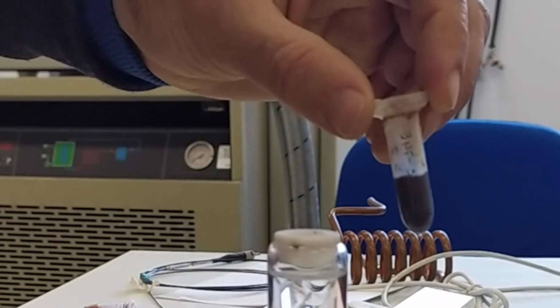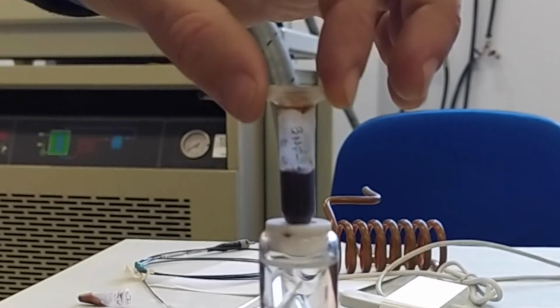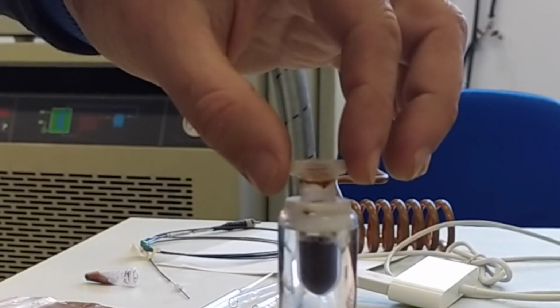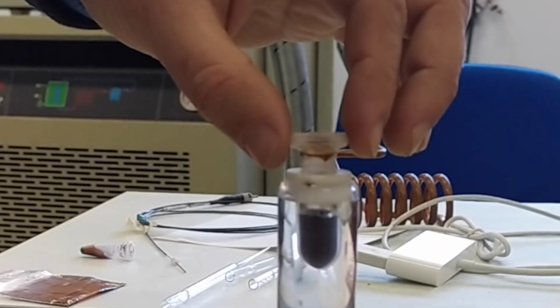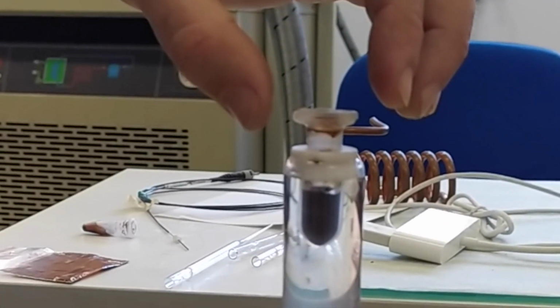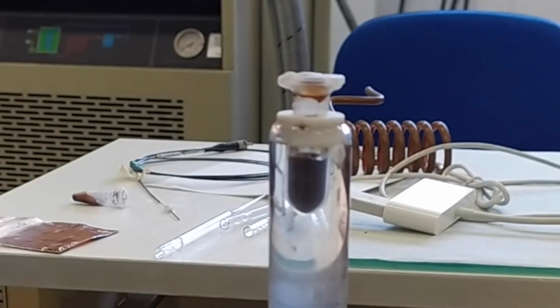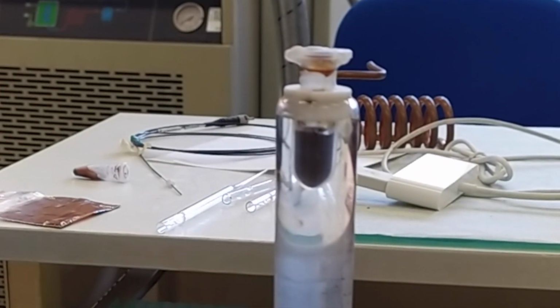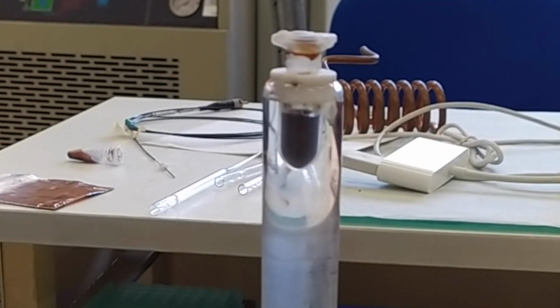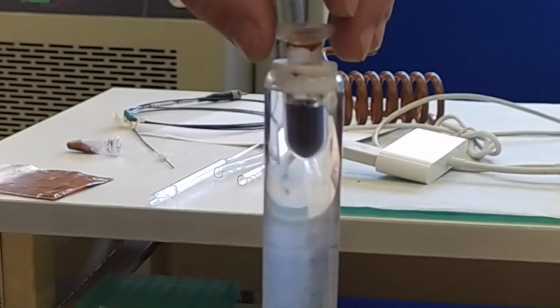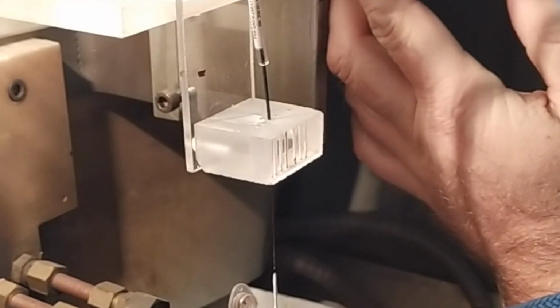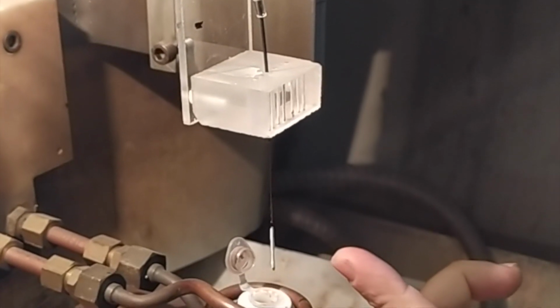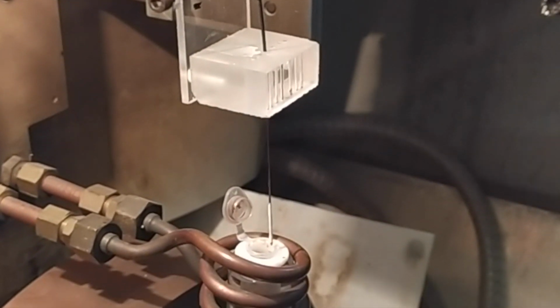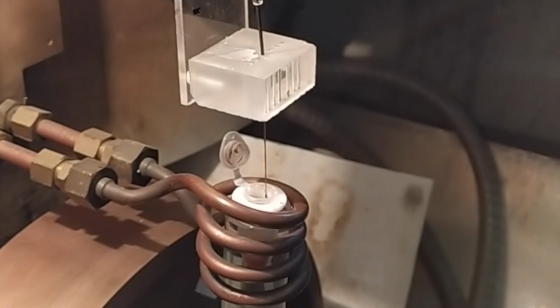Once the sample is ready, it can be put into this holder that acts both as a holder and as a thermostat. In fact, it contains water that can smooth out the heat exchange between the sample and the external environment. Once everything is ready, we lower the temperature sensor into the Eppendorf tube containing the water-dispersed nanoparticles.